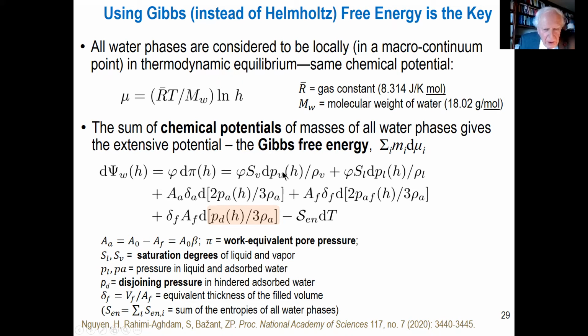Then we have a term for vapor, where this is multiplied by the concentration of vapor within the pores relative to pores. So when this is 1, it means pores are fully filled. Then liquid water, capillary water, that's the next term. Mass comes here because per unit volume it is 1 over the density of the liquid. Then the surface area of the adsorbed layers. Here we must deal with the thickness of the adsorbed layers, the number of molecular layers, 1 to 5 basically. We have the spreading pressure in the adsorbed layers, which offsets the surface tension of the solid. It goes the opposite way. And 2/3 is because this is a biaxial stress. In the third direction, there is no stress.